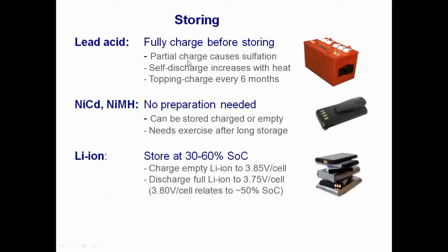Lead acid batteries should be fully charged before storing. Partial charge causes sulfation, the formation of sulfates. Self-discharge increases with heat. A topping charge is needed every 6 months. That is the charging methodology we have to follow for lead-acid batteries. For nickel cadmium and nickel metal hydride, no precaution is needed, and they can be stored charged or empty. So both are manageable, with charge or without charge. They need exercise after long storage.